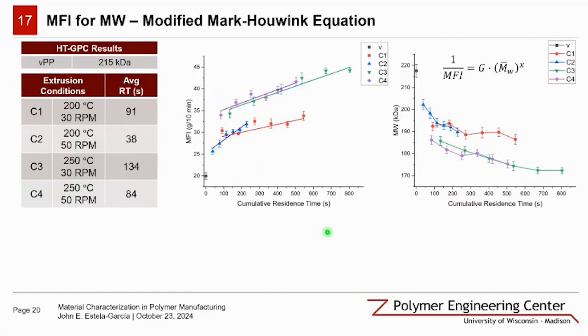There we go. The analysis of melt flow indexing in relation to the cumulative residence time reveals insights into polymer degradation during recycling processes. When we correlate MFI with our cumulative residence time, we've developed a more nuanced understanding of how processing conditions impact material properties over the repeated life cycles. So we're linking flow properties to exposure to heat and stress over time. And our data shows distinct trends for different processing conditions.